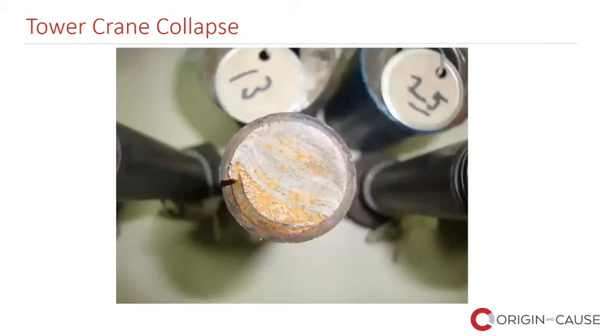In examining the fracture surface of the bolts under a low power microscope, I observed that the majority of them exhibit features which are called beach marks, which are always associated with a fatigue mechanism. All the bolts that I examined exhibited these features, indicating that fatigue was the failure mode for these bolts. Fatigue of bolts occurs when they are loose or over tightened. Regardless, it's irrelevant for this particular case because both will indicate improper installation. So when the crane was erected, these bolts were not properly tightened. They were either over tightened or they were too loose.